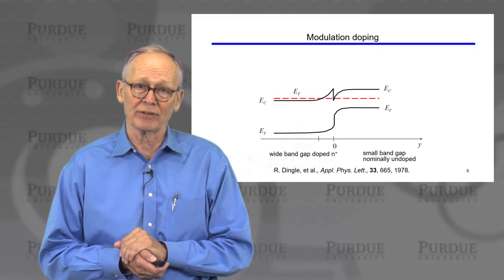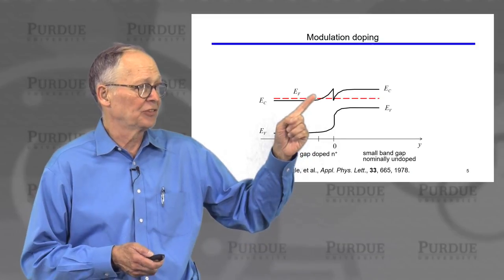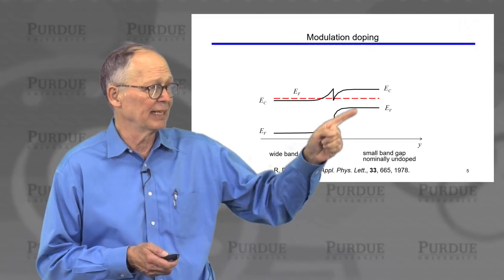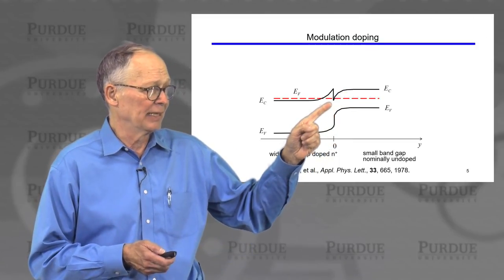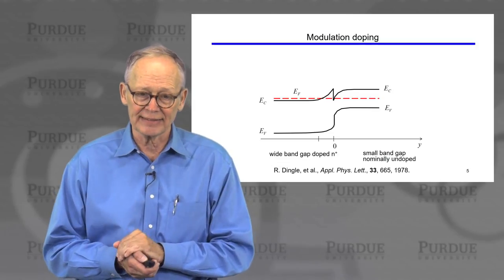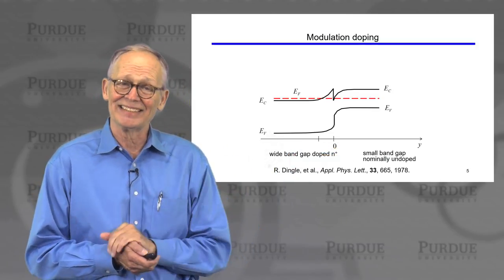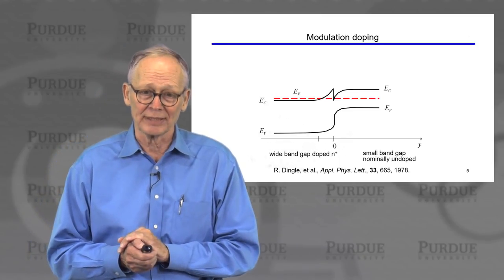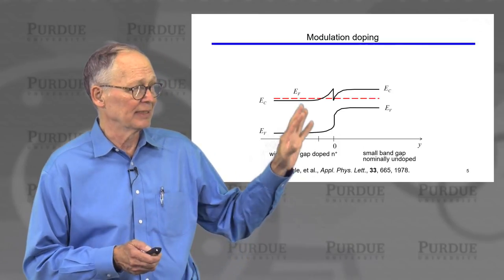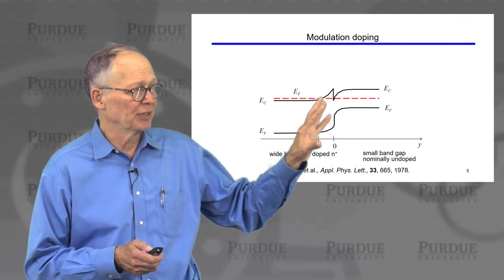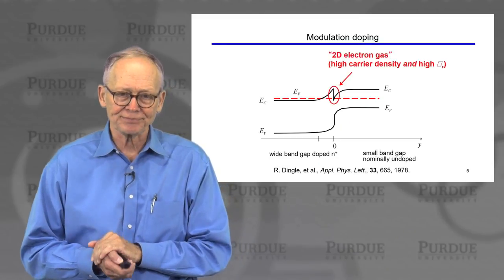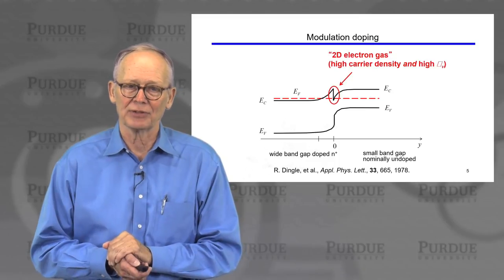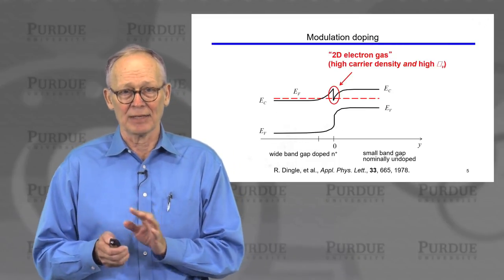When we put the two materials together, we get a band diagram showing a depletion region on the wide-bandgap side, where electrons have left and moved to the small-bandgap side. The bands bend down at the interface, indicating more electrons there. This technique — discovered around 1978 — is called modulation doping, because the dopants are in one region while the carriers are in another. The electrons at this interface form a 2D electron gas with high carrier density and high mobility.